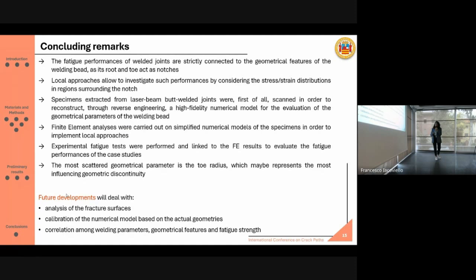So in conclusion, we know that the fatigue performance of welded joints is connected to the geometrical features, and local approaches are useful to tackle this kind of problems. In this case, we analyzed the specimens extracted from butt welded joints obtained by laser welding. And these specimens were first of all scanned in order to reconstruct a high fidelity numerical model and evaluate geometrical parameters of the welding bead. We carried out some very simple finite element analysis and some experimental tests in order to link in some way the experimental and numerical results.